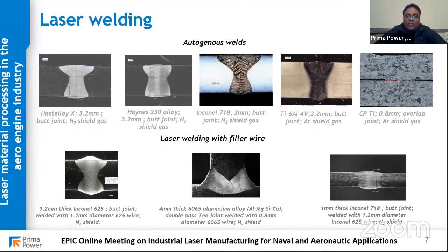So some of the examples, again, unfortunately, when you're working for aerospace people, you cannot share most of the information, it's confidential, so I can just highlight the generic data. So this is a Hastelloy X alloy, 3.2 millimeter butt joint. Again, you can see very nice, no porosity, no cracking. Haynes 230, Inconel 718. And there's also some requirement for welding this material using a filler material, because in some cases the fit up is not so good, or there are metallurgical requirements, so we end up using filler.